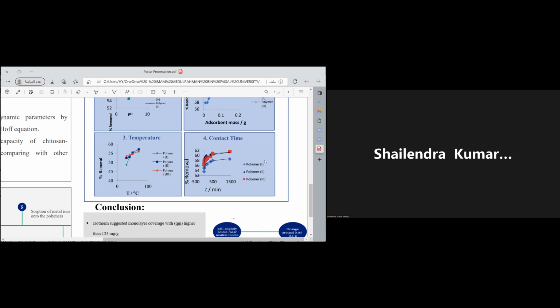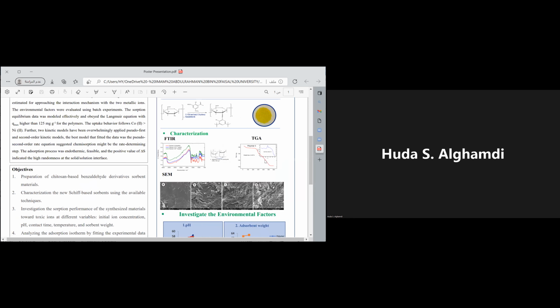Also, we studied the isotherms, thermodynamics, and kinetics. These are the modeling studies. These studies predicted the performance of the sorption process. For the thermodynamic parameters, delta G illustrated the spontaneity of the process. It was negative. Delta S indicated high randomness at the solid solution interface. And delta H was positive, so this was an endothermic reaction in nature. For kinetic studies, we applied pseudo first order and pseudo second order models. And the process was perfectly described by pseudo second order. So it demonstrates that chemisorption is the rate determining step.